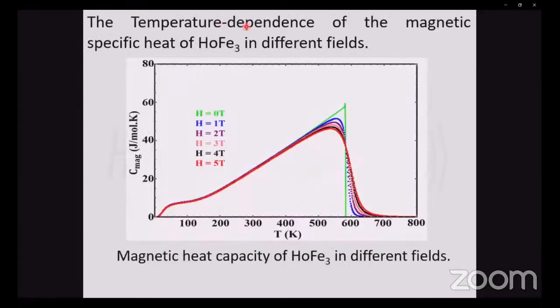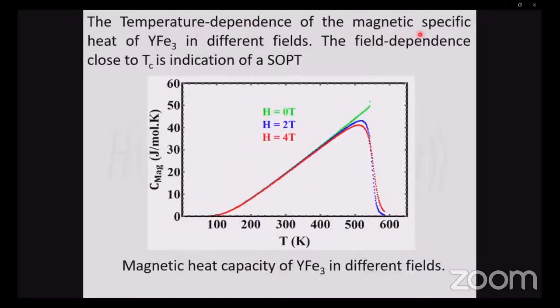The results of heat capacity. The temperature dependence of the magnetic specific heat of holmium iron three in different fields shows that the heat capacity reduces as we increase the external magnetic field. The temperature dependence of the magnetic specific heat of yttrium iron three in different fields. The field dependence close to Tc is an indication of second order phase transition.